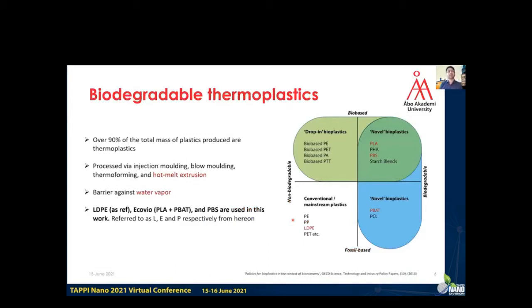And speaking of biodegradable, let's look into thermoplastics, or plastics in general. Over 90% of the total mass of plastics produced are thermoplastics. And in this work, we used hot melt extrusion to process these into thin layers onto the paperboard. The main advantage of using thermoplastics is their barrier against water vapor. And the figure to the right separates different kinds of thermoplastics into different categories. Based on their source, they can be fossil fuel based or bio-based, or based on their end of life, they can be non-biodegradable or biodegradable. And the best thing would be to have a material that is both bio-based and biodegradable. That would be the holy grail of barrier packaging.